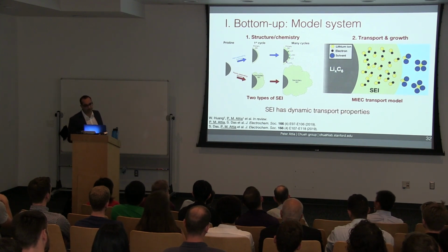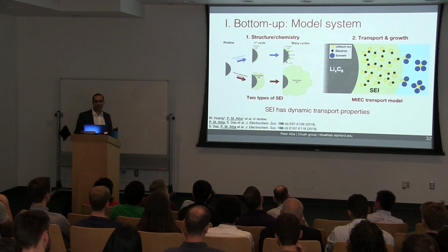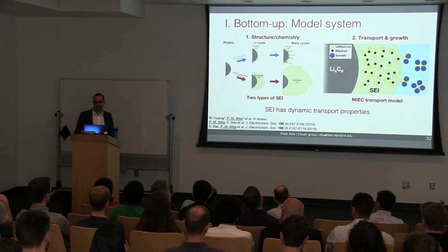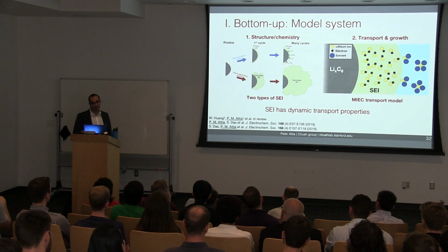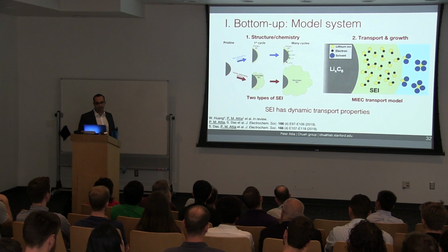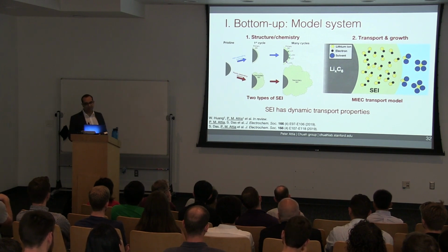I think the biggest takeaway from this section for me is that the transport properties of SEI are dynamic. As an experimentalist, I often think my goal is to identify the most important properties of a system so that we can develop a theory around it. And there are countless SEI modeling papers, but almost all of them treat the SEI kinetics as static. It seems reasonable given how thin the layer is. But what we found here is that this assumption is way off. The kinetics are highly dynamic. I think this holds not only for the SEI on graphite, but also the SEI on silicon, lithium metal, and other chemistries as well.